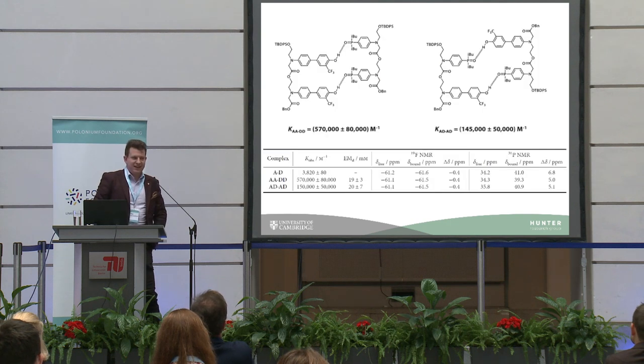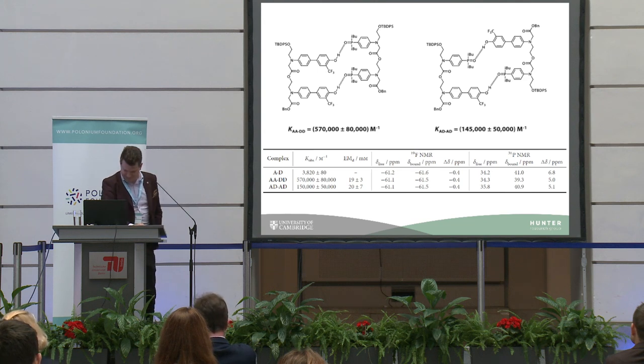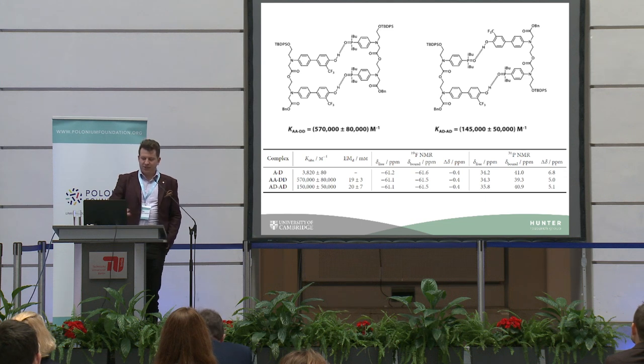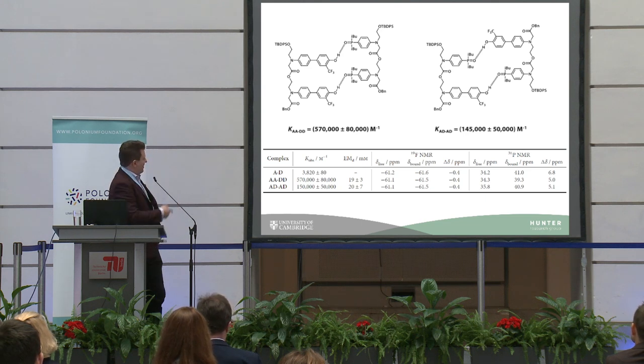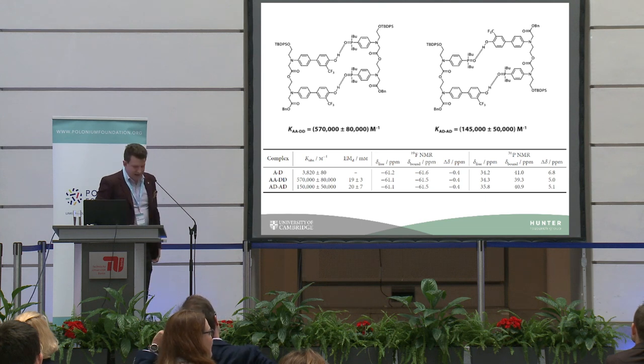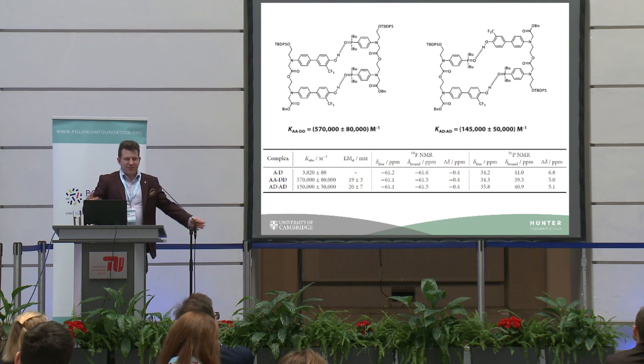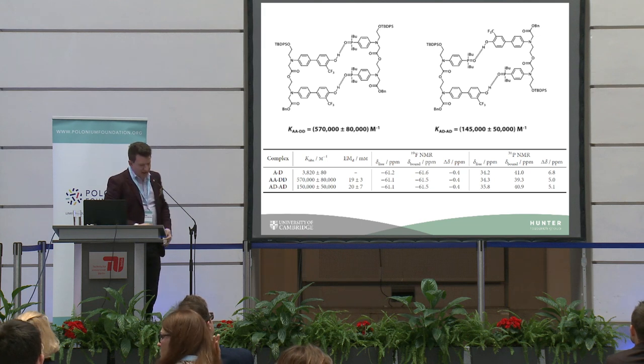I synthesized molecules where you can see half a donor — the phenol site is the donor and the phosphine oxide site is the acceptor. Using our nomenclature, the molecule on the left is a DD dimer and the one on the right is an AA dimer. They bind quite strongly — roughly a hundred times more strongly than if the two sites were not adjacent to each other, which means they are acting cooperatively. So we already know they form hydrogen bonds and closed duplexes.